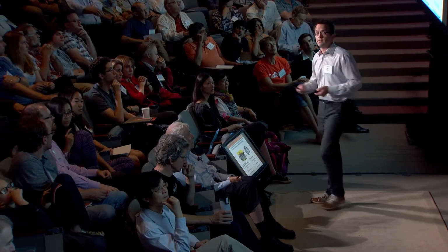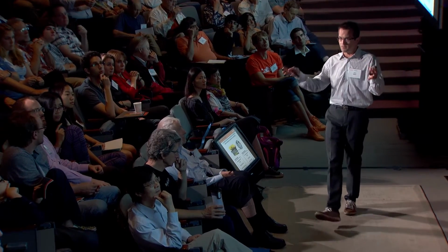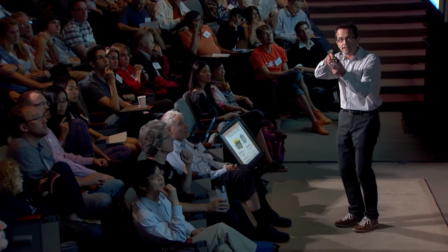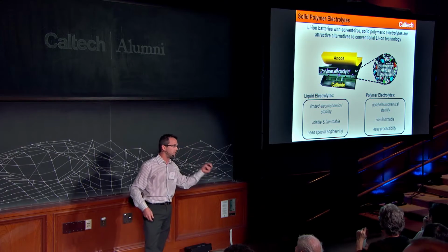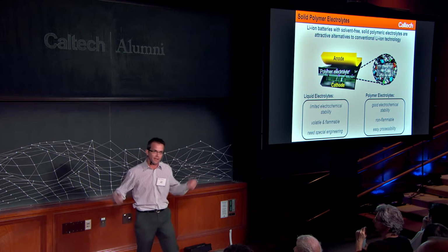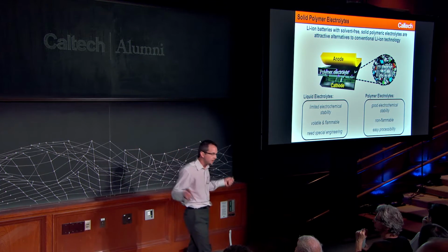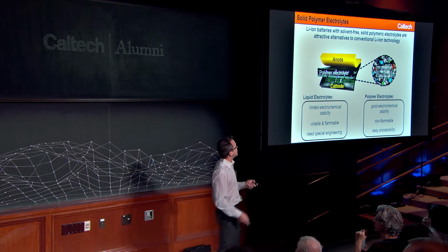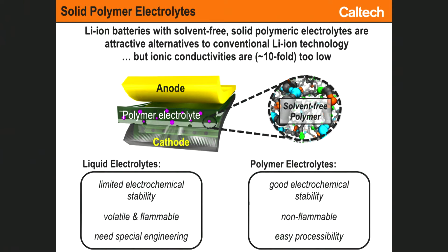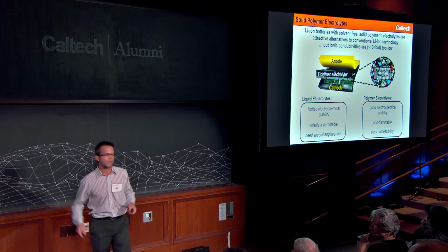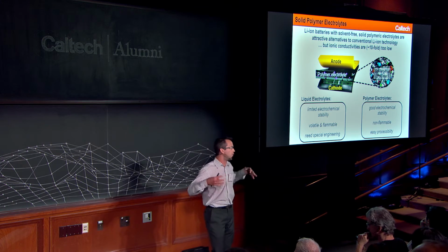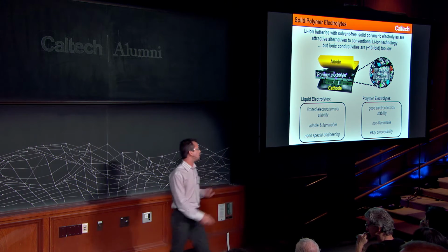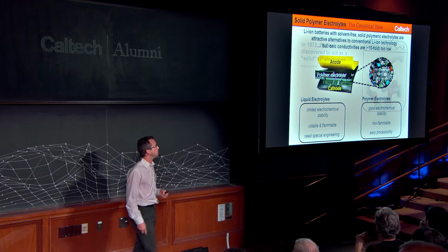The downside is the one point of a battery electrolyte is to get the ions through quickly, to get them from one side to the other side fast. And what we all know from the polymers that we interact with in our daily life is that they're incredibly sluggish materials, and as a result, the rate of that ion conduction simply tends to be too slow. So this is the essential design challenge. How can we get the benefits of polymers while getting fast conduction of the ions through the battery material?